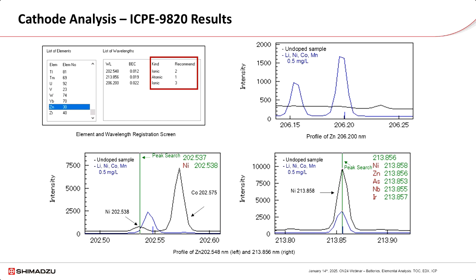For this reason, it's important to select the best wavelength that is interference-free. Take zinc as an example. The ICPE solution software recommends 3 best wavelengths to choose to quantify zinc, as highlighted in the red box of the upper left figure. As shown in the lower figures, the software allows users to check which element has peaks that are likely to overlap with the target element using the peak search function.